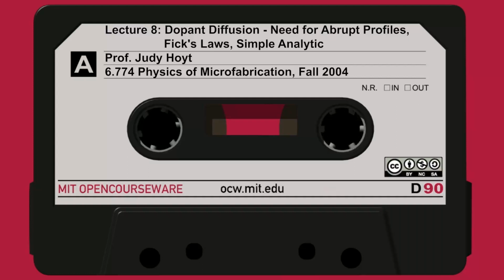Now we make the assumption at this point that the diffusivity is constant, so it doesn't depend on x. In that case, and only in that case, we can pull the D out of the derivative, because the partial of D with respect to x, by the chain rule, is 0. Then we get the equation at the bottom of the page, which says that the time rate of change of the concentration at any given point is a constant D times the second derivative of the concentration with respect to x. That is Fick's second law. Again, this particular formulation only applies if the diffusivity is a constant. It doesn't depend on x.